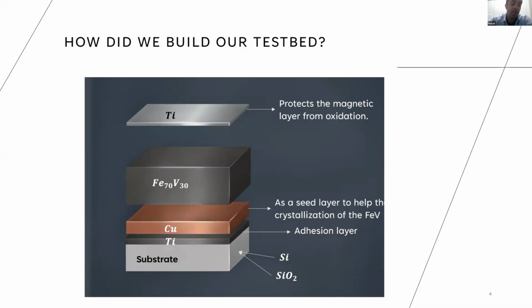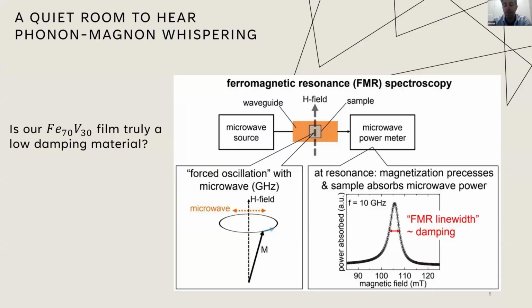And there is another problem. Iron vanadium rusts the moment it touches the air, so we need a protective layer on top. Our choice is a thin layer of titanium because it's very reactive and can build a skin as a shield. The other thing we have to consider is that our substrate is either bare silicon or thermally oxidized silicon, and unfortunately, copper doesn't bond well with its glassy surface. So we need an adhesion layer. Our adhesion layer is again a thin layer of titanium because it's highly reactive and can form a strong chemical glue to our substrate. After making our sample, we need to know how we do our measurements.